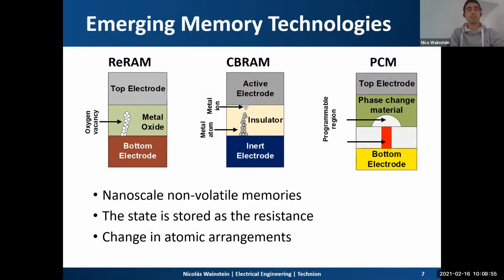These devices share the characteristic that the state is stored as a resistance. Resistive RAM is based on defects in the thin metal oxide layer, called oxygen vacancies, which can be modulated to form a metallic filament, which will change the conductivity of the insulating layer. CBRAM, in turn, relies on redox reactions in the active electrode, which provides ions that migrate along the electric field to the inert electrode, where they are reduced, forming a metallic filament, which also changes the conductance between the bottom and top electrodes. Finally, PCM relies on the large conductivity contrast between the crystalline and amorphous phase of chalcogenide phase change materials.